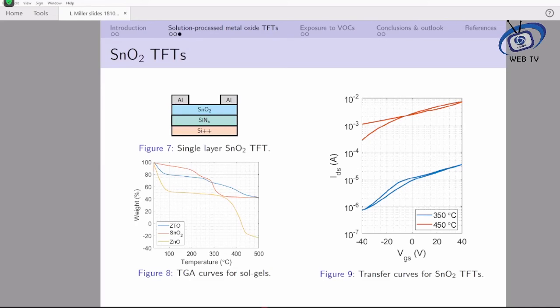The weight reduction prior to 200 degrees Celsius was attributed to the evaporation of the organic solvent used, which was 2-methoxyethanol. The changes recorded from 230 degrees C to 300 degrees C represented the decomposition and separation of the chloride ligands in the precursors. No further weight loss was recorded after 450 degrees Celsius, which indicated that a dense metal oxide network had formed.